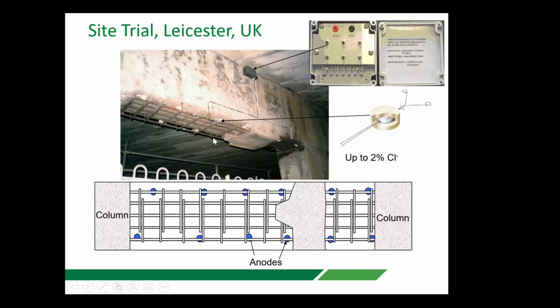We removed 2 adjacent areas. We removed the cover concrete, exposed the steel that was corroding, and then attached 8 anodes around this area and 4 anodes around this area. As you notice, it's at the periphery of the patch. But instead of connecting the anodes directly to the steel reinforcement, we took the connection into a junction box, connected the junction box to the steel reinforcement, and therefore we were able to turn on and off the galvanic anodes.